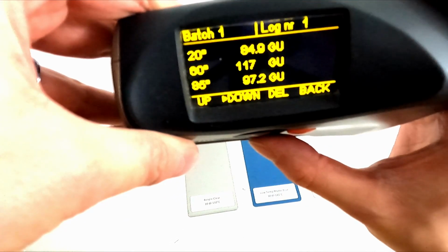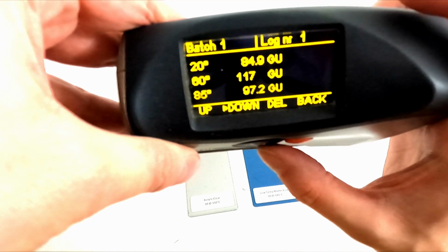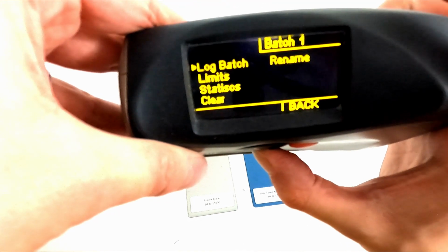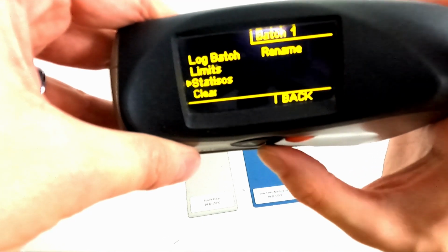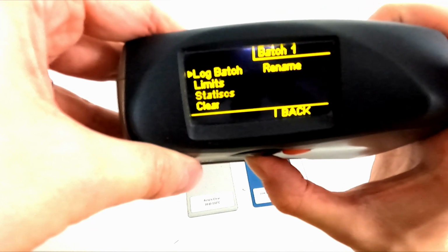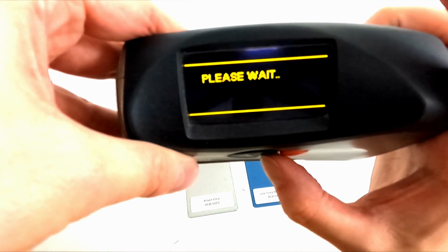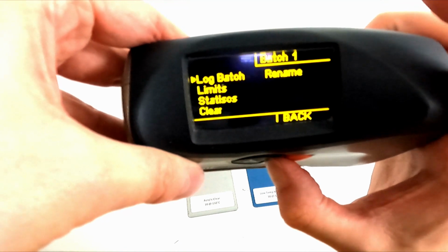It's good practice to evaluate your powder coatings on test panels before committing them to an actual part, and a 3x6-inch test panel provides a good amount of space to take and average multiple gloss readings to produce an accurate measurement. If you have to check the gloss of a coating on a finished part, try to evaluate on the flattest and largest area of the part, as any curvature can skew the results. It should also be noted that variations in the coating's thickness and texture, as well as differences in how it is applied and/or cured, can influence the gloss of the coating.